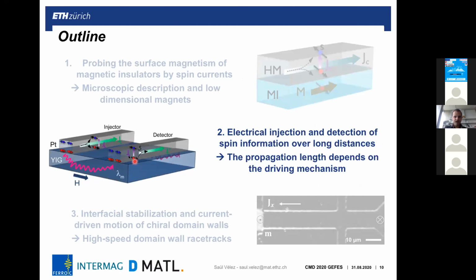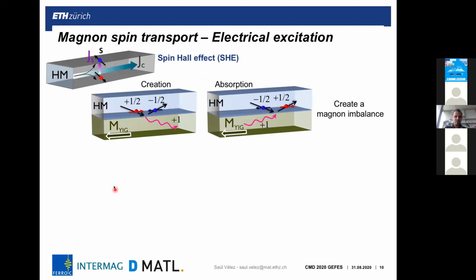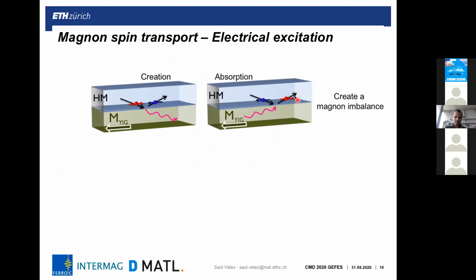So in the second part, I would like to show you that we can excite magnons and detect them by electrical means. So now, considering again the spin Hall effect, when we have the spins that are parallel to the magnetic moment, we can excite magnons. We can either create or annihilate magnons in the magnetic insulator, but also we can absorb them and detect them by charge currents. So how does it work?